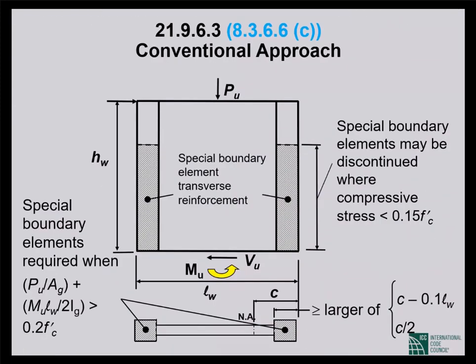Okay. So now the trigger is this combined compressive stress exceeding 20% of f'c. This is not greater than or equal to, this is greater than. Now, I want to stress very emphatically that when we go back to the old trigger, the extreme fiber compression stress exceeding 20% of f'c, we do not go back to neglecting the web of the shear wall in designing for flexure and axial load. We never do that anymore since ACI 318-99. The entire shear wall section counts.